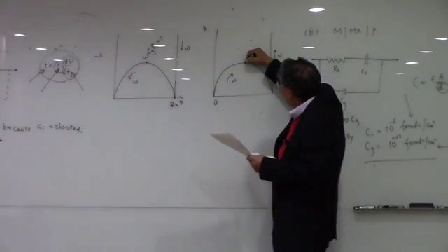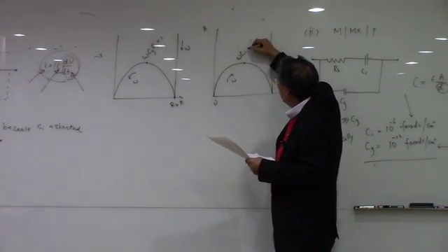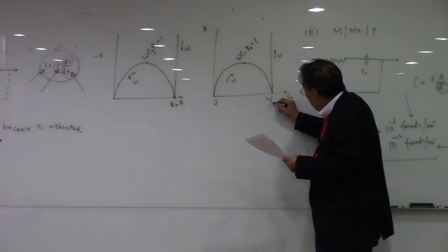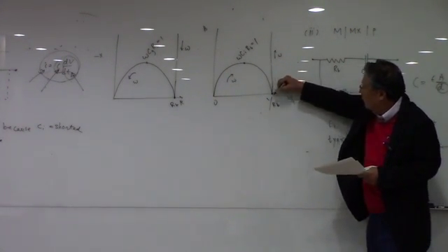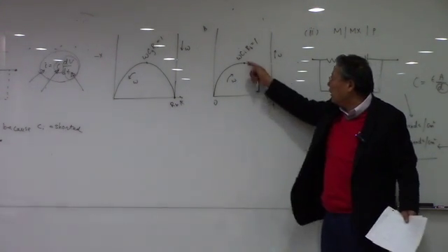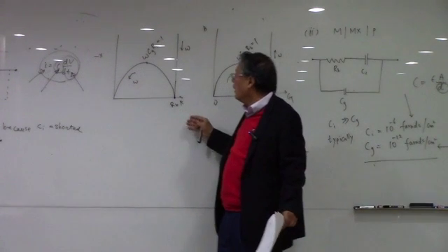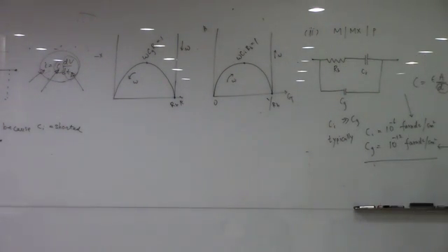And then the maximum point here now corresponds to omega Ci Rb equal to 1 here. And then here is going to be 1 over Rb, the point here. So we can have information about the Ci with this plot, and then Cg with this plot, and then we can separate out the bulk resistance.